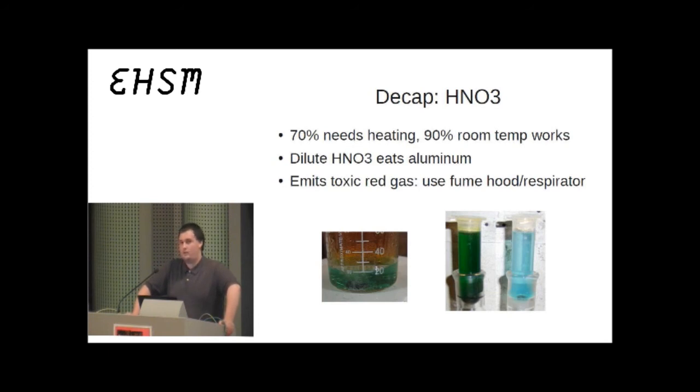It varies wildly what you need to do with it, depending on the concentration. So 70%, for example, which is what tends to be a little easier to get, down to maybe about 60%, you definitely need to heat it. But if you have 90%, the so-called fuming nitric acids, such as white fuming or red fuming nitric acid, you actually don't even need to heat it. In fact, it'll even self-heat, and if you're not careful, can even more or less explode, just left at room temperature. So that has to be watched a little more carefully.